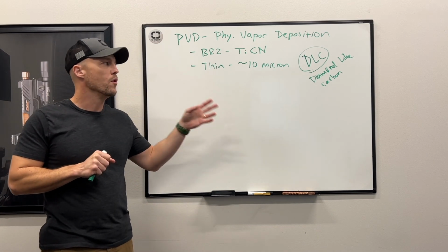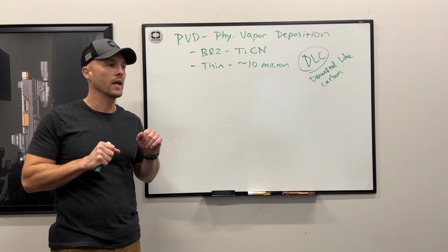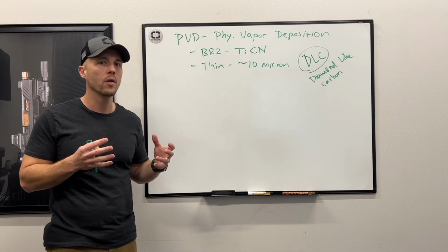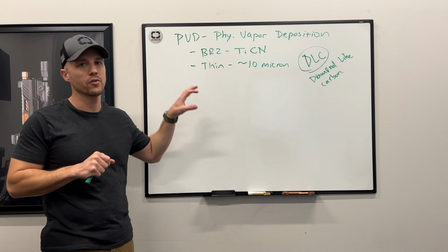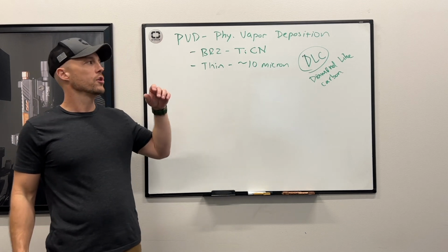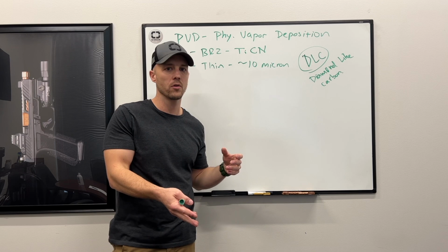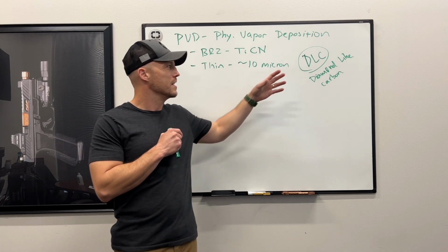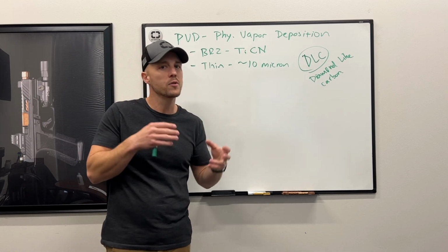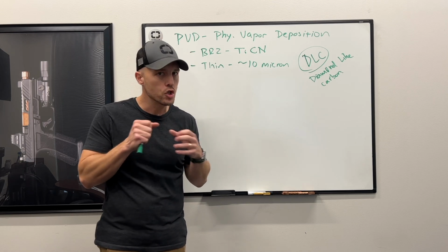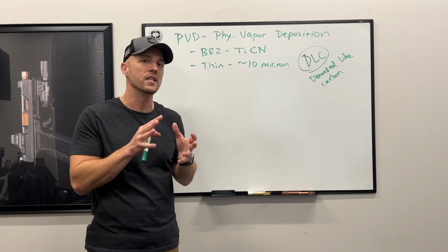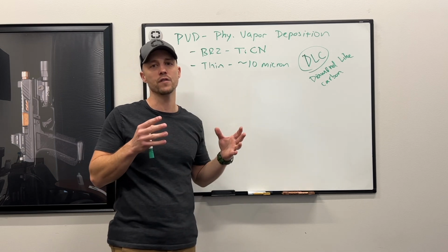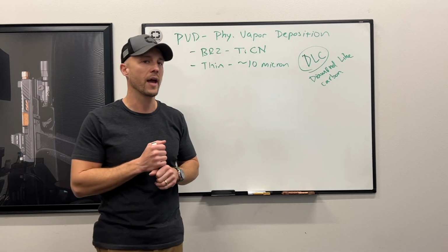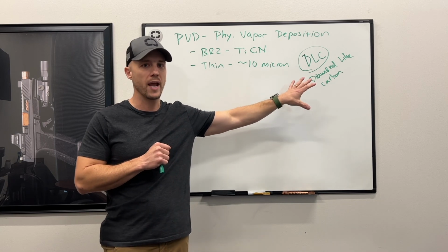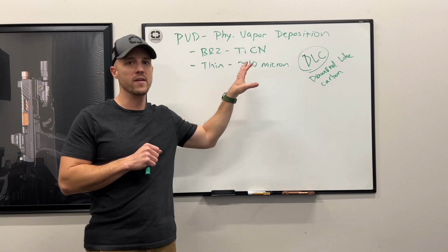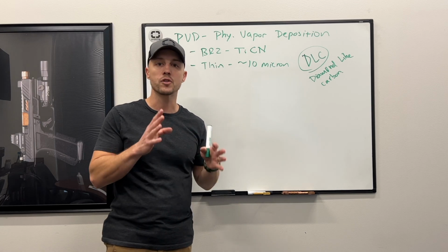One of the reasons that we moved away from DLC was that even though it holds up really well, again, you're not changing the characteristics of the steel underneath it. So your limitations, like if you drop a part or something like that, the DLC may not have failed, but the substrate underneath it, unless it's super hard, is prone to deforming, and then you'll almost have the finish fail because the steel underneath it failed. But DLC as a standalone finish is great, though again, it's very thin, and like all PVDs, it doesn't actually change the substrate, the material itself.